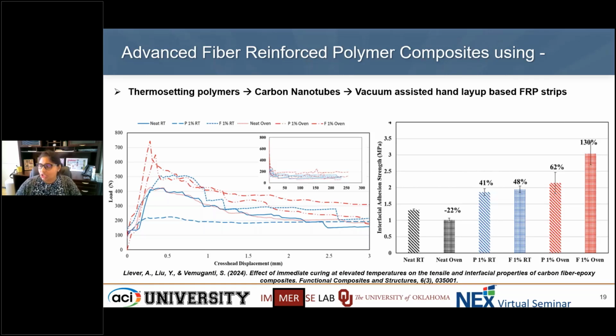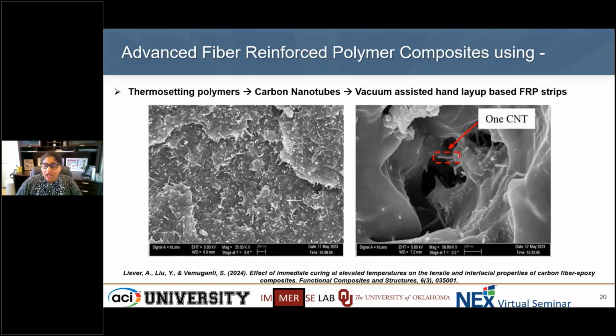So we looked at tensile capacities, shear capacities, and now interfacial adhesion strength. If we look at how these nano modified polymeric resins show us the nanotubes, we performed some SEM investigations. Because these CNTs are highly dense particles, it's very important to achieve a good dispersion, and several factors play into effect. And this paper is one of those, studying the relation between temperature or heat and the energy that it needs to cure well and disperse well. So if you see, this is one carbon nanotube here poking out from the polymeric matrix, of approximately a scale of 20 to 30 nanometer in diameter and 15 to 20 micrometer in length.